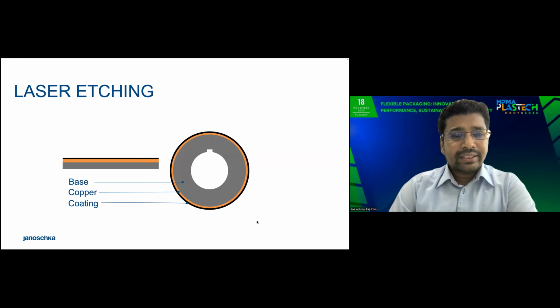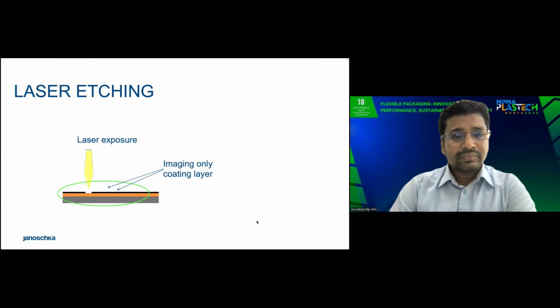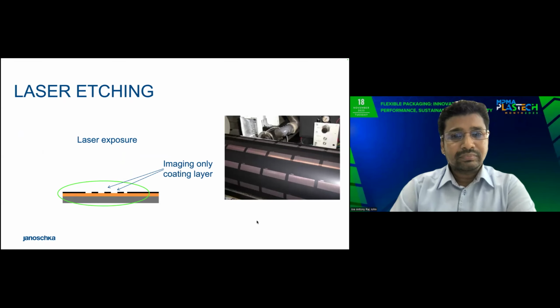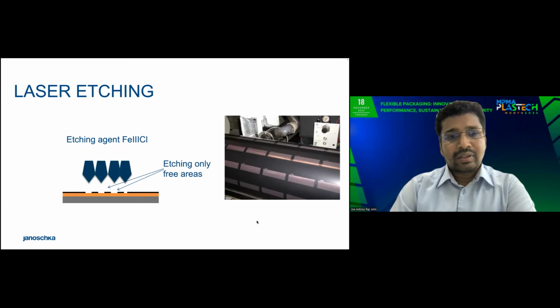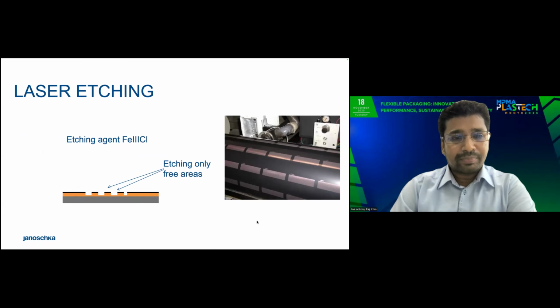So the laser etching has its coating on top of the copper. The laser is exposed on top of the coating. That's how the coating looks. Then the chemical agents remove the exposed coating and penetrate to the copper.